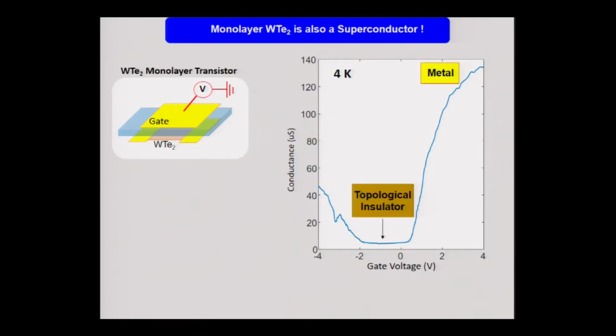So this is the data we have, the conductance as a function of the gate voltage you apply here. This here is the insulating state, but the insulating state still has some finite conductance. That's because the edge is conducting. So it's a topological insulator. And then if we change the gate voltage to a high value, you add electrons to the system, and the system becomes metallic, which means now you actually realize a transistor tuned from off-state insulator to a metallic state.